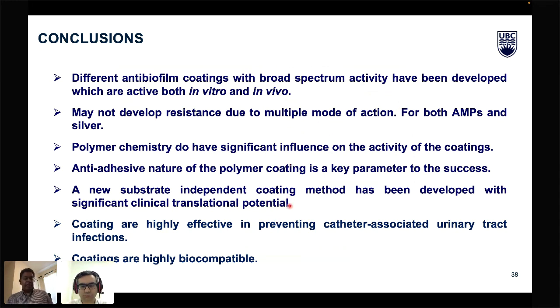And the polymer chemistry part is an important aspect, the screening of diverse polymers, finding the right molecular weight and what density of the functionality, all of those things are important in generating this coating. And most remarkably, the anti-adhesive nature of the coating in combination with the antimicrobial agent is able to provide this long-term activity. And this coating is substrate-independent and can be applied to diverse substrates. And I have shown that these coatings are effective not only in vitro in the lab, but also in a mouse model as well as in a pig model, so it has good translation potential.